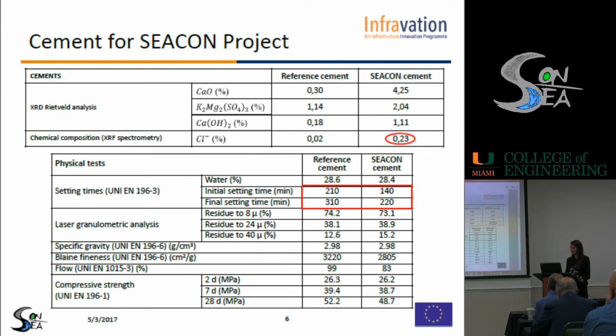In fact, this is a waste material coming from cement production, and its reuse is limited because of its chloride content. You can see from the table that SEACON cement has a chloride content of 0.23%. The limit is 0.1, so it exceeds the limit, and is much higher compared to the chloride content of the reference cement, which is 0.02%.